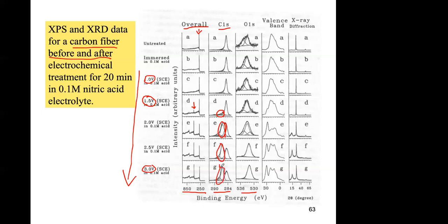And this is incredible, remember, you're oxidizing the carbon fiber. The oxidation occurs on the outside of the fiber. So you have a fiber of this form, and you're forming an oxide on the fiber. You still have the carbon inside, pure carbon. But since this is a surface analysis technique, you're looking at the surface of the fiber. So you're basically looking at the oxide formation. And this is very nicely seen here in the carbon 1s binding energy.